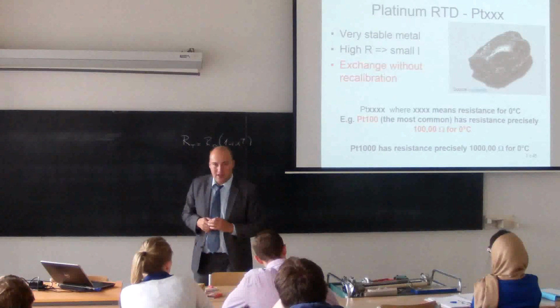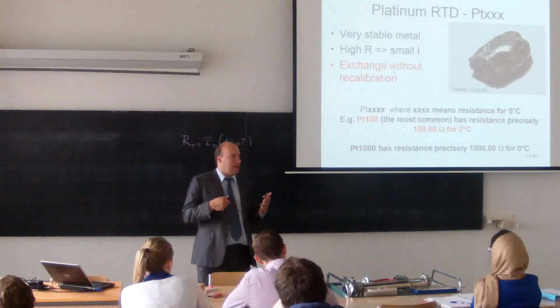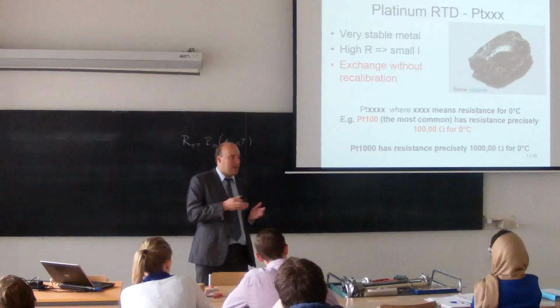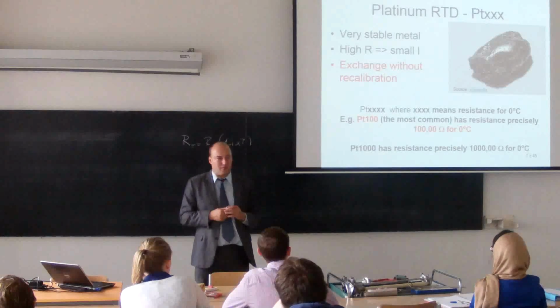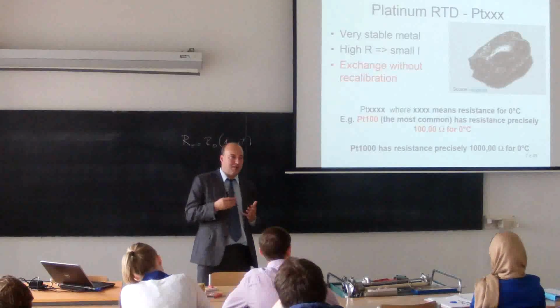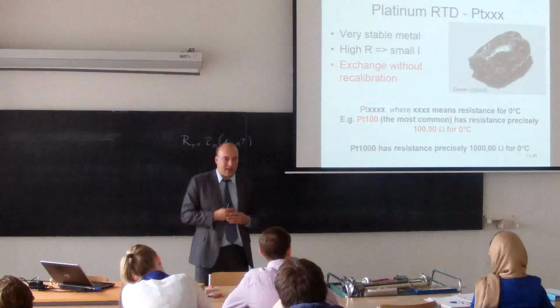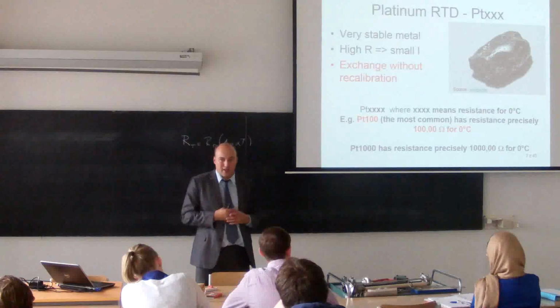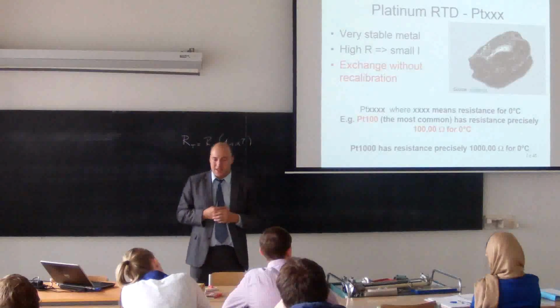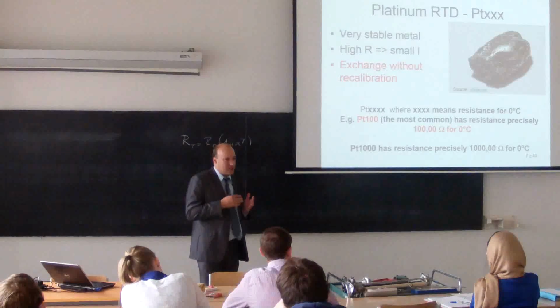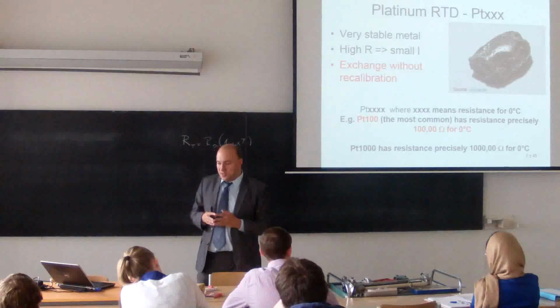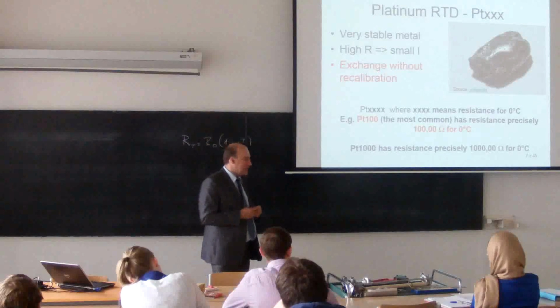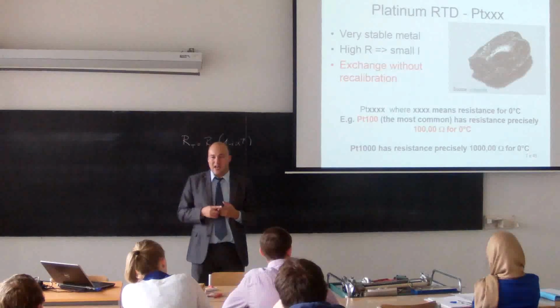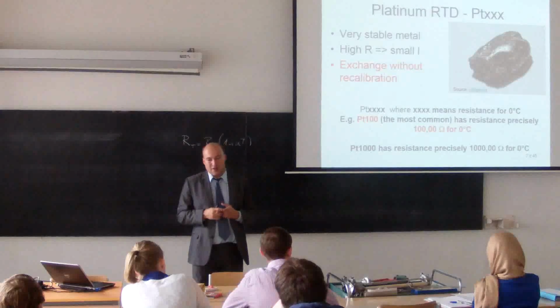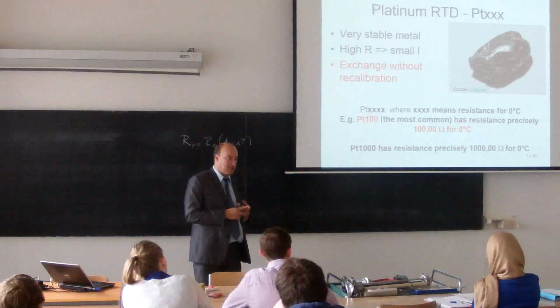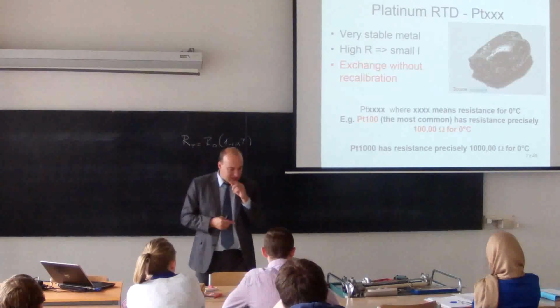If I need to measure the temperature in my application, and a little bit later, for some reason, I need to exchange the sensor, I just take the same type of sensor, place it in the application, and I don't need to recalibrate the whole work. That is the biggest advantage of this platinum sensor. For those three reasons, the platinum sensor is the most common type of sensor used for temperature measurement, although it's expensive. And there are several types.